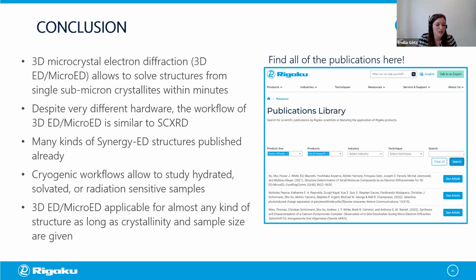Which will surely increase even more, especially with the continued development of new features for the Synergy-ED. And with cryogenic workflows, allowing to study hydrated, solvated, or radiation-sensitive samples, so that in the end, we can really measure basically any kind of structure as long as the crystals are small enough and are actually crystalline. And if you want to have a look at a specific publication that I mentioned throughout this talk, we do have all of them listed on the Rigaku webpage, so you can look them up there.